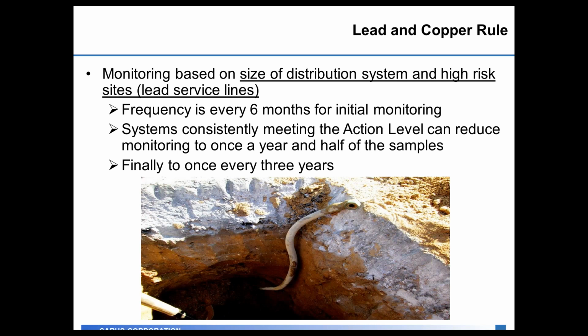The monitoring for the lead and copper rule is based on the size of the distribution system and the high-risk sites that you have out in the distribution system. High-risk sites would be places where you know you have lead service lines or you have copper plumbing in the consumer's home that has lead solder. The original frequency is every 6 months for monitoring of the lead and copper rule.